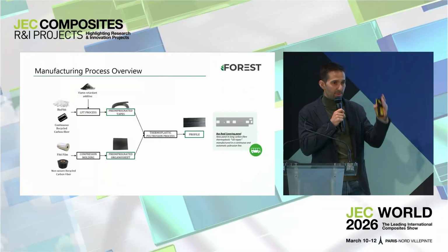And here we have a schematic, an overview of the manufacturing process. It all starts with recycled continuous carbon fiber, the biopolyamide 6, and some flame retardant additives, which are mixed together in LFT, a long fiber thermoplastic process. With this process, we obtain the thermoplastic UD tapes on one side. So we tested these materials in a pultrusion system, but we obtained preferential properties in one direction.